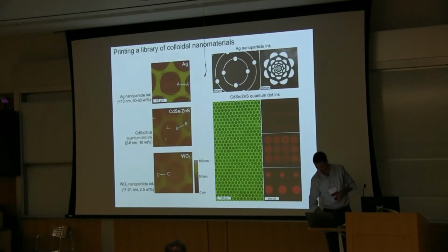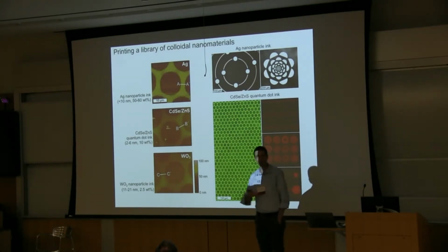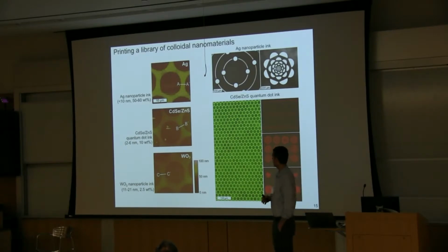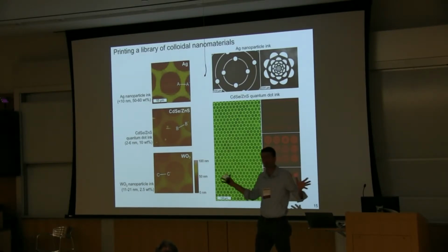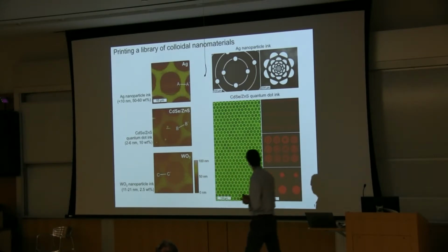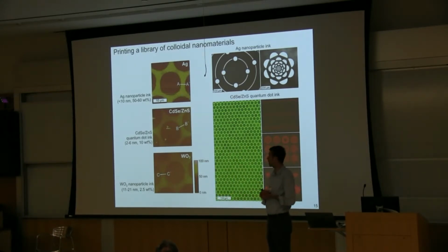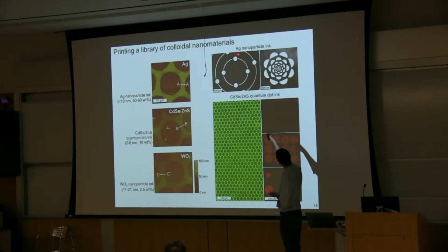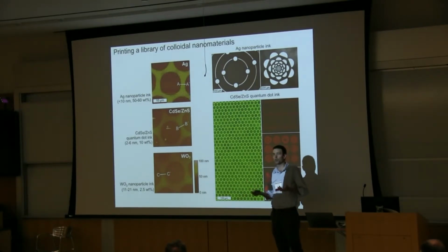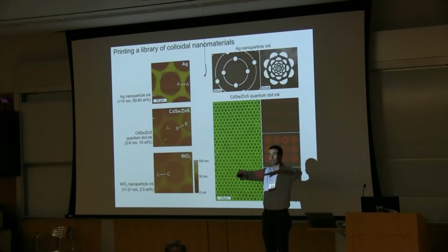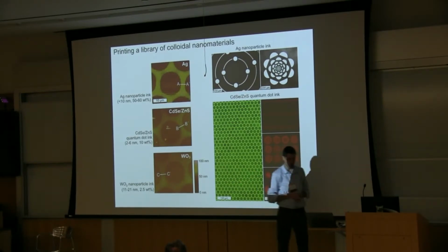We're obviously interested in printing things other than simple silver inks. It would be really awesome to print functional materials, oxide semiconductors, and for example, we've shown, simply using commercially available materials, that you can print semiconducting quantum dots of different colors. These are core-shell quantum dots. And then another thing you can do is print narrow and broad features at the same time. Those are just kinds of things you can't easily do in droplet-based printing processes because the layers you print are thicker and the capillary forces dominate.